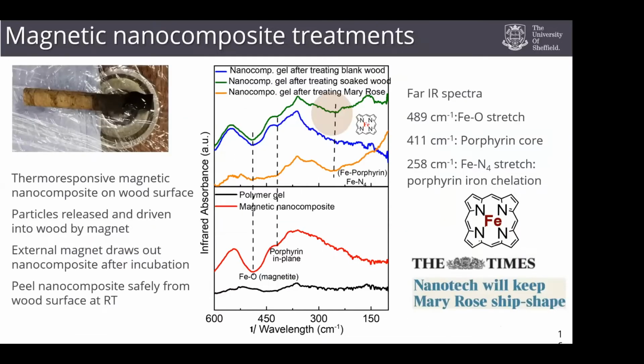This is a sample of the Mary Rose wood, and that darkened region there, it's dark because there's lots of iron present in this particular piece of wood. That shiny black blob is your iron oxide nanoparticles, and by using infrared spectroscopy, we were able to locate where we have the iron bound to a porphyrin, which is what we used as our binding agent on the surface of these nanoparticles.